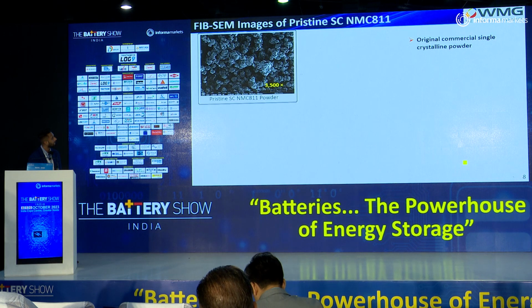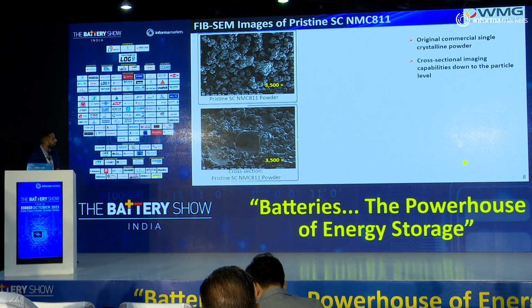So, what did we do with these cells when we coated them, and what other capabilities do we have at Warwick? Well, we can go all the way into the SEM images and look at the powder on a microscopic scale. So this is 3,500 times magnification. And we also have a FIB SEM, where we can selectively target individual particles and cut into them to see what the particles are like inside.